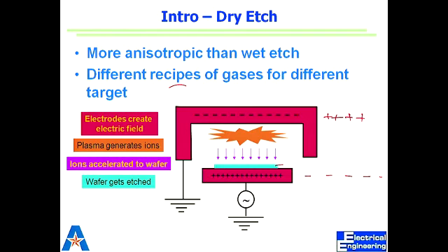So reactive ion etching or ion beam etching is actually the combination of these two. So they are directional, they are reactive. You can see that we have a positive plate and a negative plate, and your target or the substrate is always at the cathode, connected with the negative plate, so that those positive ions that need to be bombarded on the target move towards the target substrate.